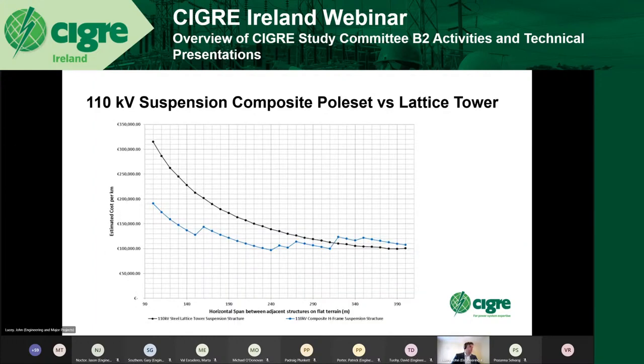Looking at this example where a composite pole set was compared to a 110 kV steel lattice tower. So similar to the last one, but what you find with the towers is that they have similar design lives or service lives. But when you compare the steel lattice tower to the composite, there's obviously an optimum span to use the steel lattice towers at. So this example illustrates that. Typically, which is the black line here, it's in and around the 400 meter mark in this example. And you can see the composite, when you compare it, is obviously costing less, up to about 300 or 320 meters, and then it goes slightly over.